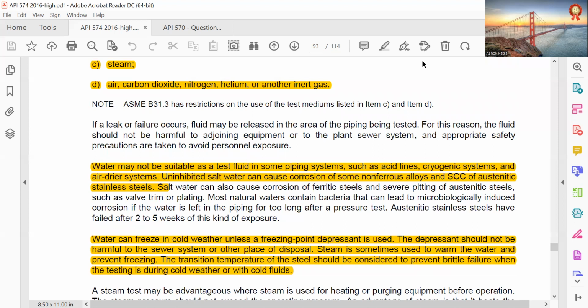Water may not be suitable as a test fluid in some piping systems such as acid lines, cryogenic systems, and air dryer systems. Uninhibited salt water can cause corrosion of some non-ferrous alloys and SCC of austenitic stainless steel. Salt water can also cause corrosion of ferritic steel and severe pitting of austenitic steel, such as valve trim or plating. Most natural waters contain bacteria that can lead to microbiologically induced corrosion if the water is left in the piping for too long after a pressure test. Austenitic stainless steels have failed after 2 to 5 weeks of this kind of exposure.